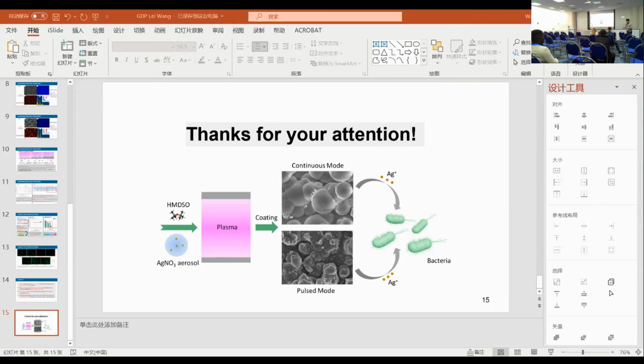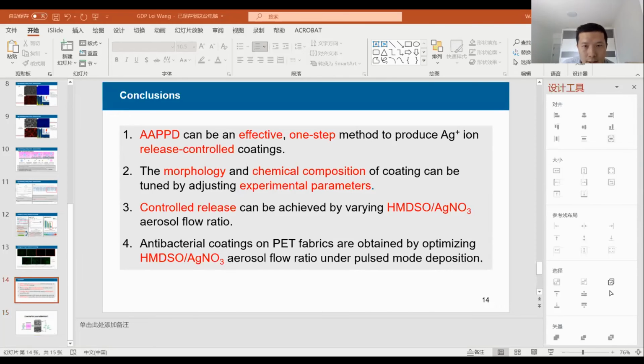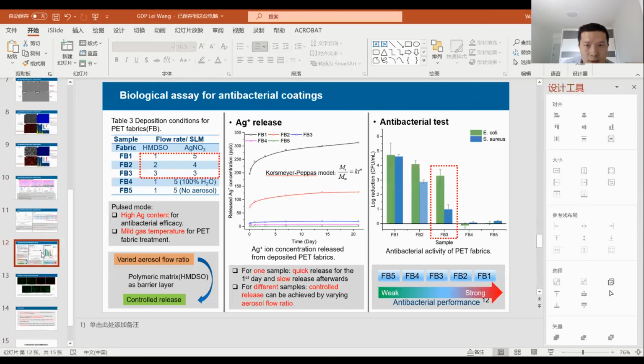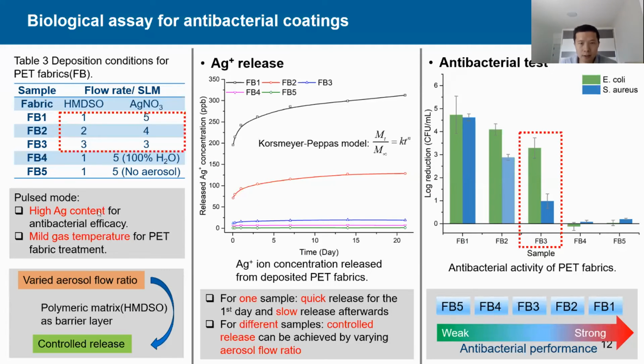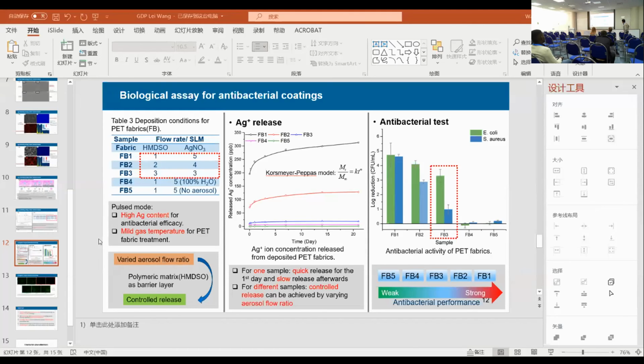Dr. Wang, how long is the antibacterial effect of your coatings? How long? Days, weeks, years, maybe? I can show you a slide here. First, we can look at the silver release curves, and we did the test for 21 days. It takes so much time, and I think it's a good idea to check how long the antibacterial coatings give good performance.